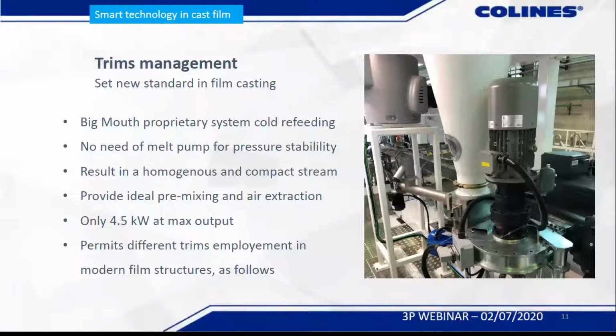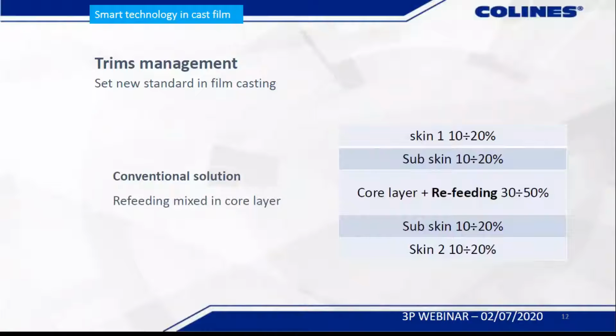And it permits also to add trims coming from other rooms, like for example the slitting unit. But it can be employed in 2 ways. The first way, the conventional solution that we've been using since long and still are using, is refeeding the trims in the core layer. So making the mix in the core, normally homopolymer layer or LLDPE, even metallocene with stretch, but anyway in the core layer. The film you see here is for a CPP MOPP film.